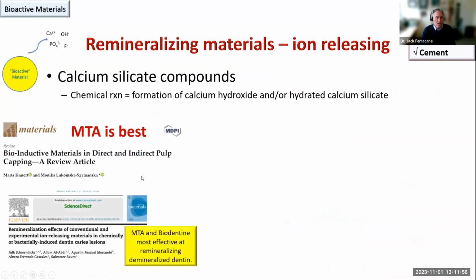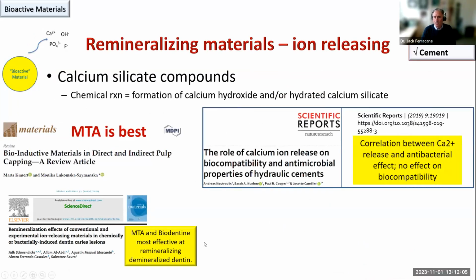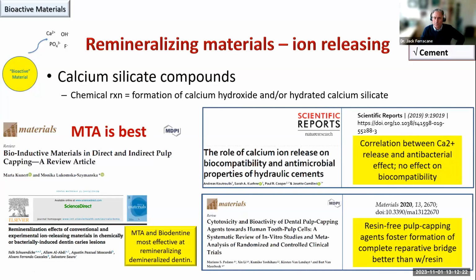We see studies which have shown that MTA and Biodentine are more effective at remineralizing demineralized dentin in comparison to calcium hydroxide. And we see a study here which shows that there's a correlation between the amount of calcium released and an antibacterial effect, which again we understand because calcium does have an effect on bacteria. And these materials do tend to be very biocompatible.